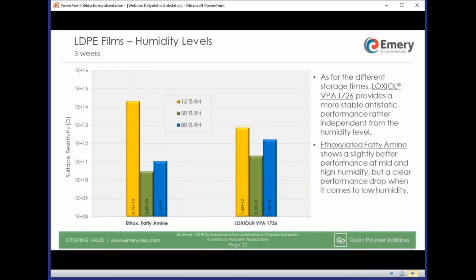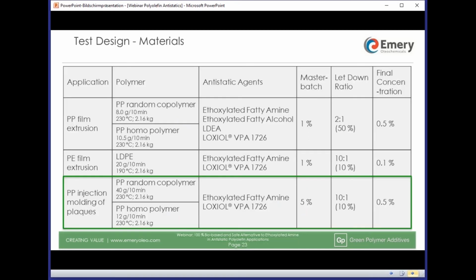PE films once more. Now we look at the influence of humidity. Interestingly, a similar picture as on the previous slide. LOXIOL VPA 1726 is more stable in performance. Ethoxylated fatty amine shows a slightly better performance at mid and high humidity, but it has a problem at dry conditions. We have seen this to a minor extent in PP films already. Good, let us leave PE again.